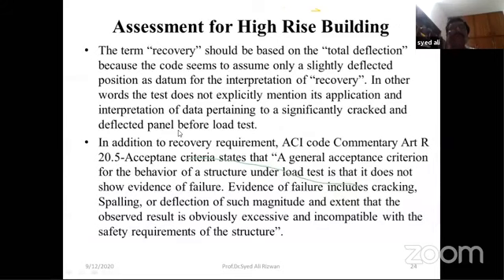Assessment for high-rise building. The term recovery should be based on the total deflection, because the code seems to assume only a slightly deflected position as datum in the interpretation of recovery. In other words, the test does not explicitly mention its application and the interpretation of data pertaining to a significantly cracked and deflected panel before the load test. These same were my comments in the case of Pace Shopping Center.